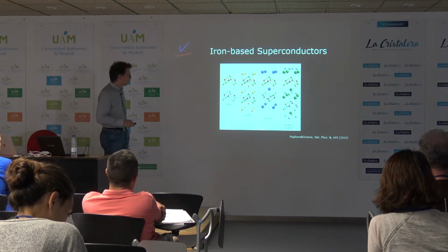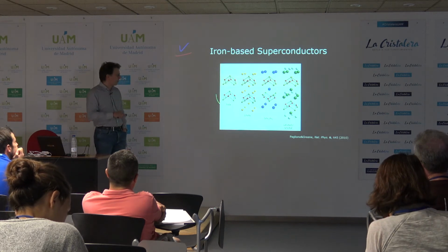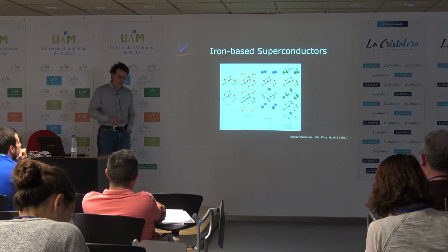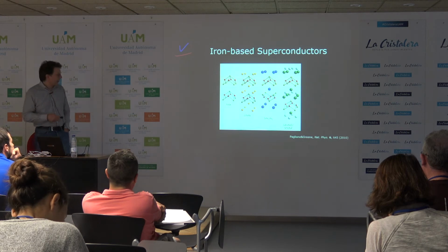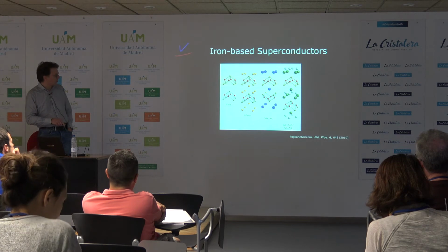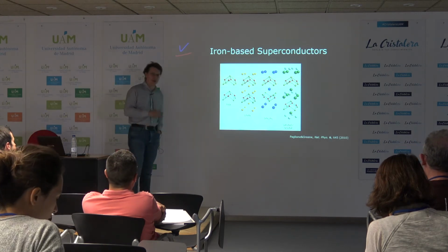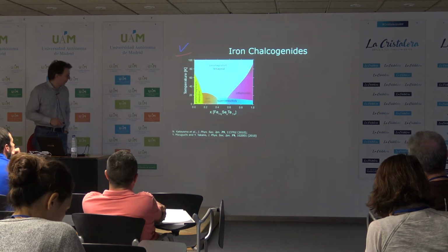the iron chalcogenide superconductors. And one of the reasons why we chose to study iron tellurium is because if you cleave the material, it's a non-polar surface, and you don't cleave into any of the dopant layers as you would do in the 1,2,2 compounds or the 1,1,1,1 compounds. So you can assume that your surface is reasonably representative of the bulk material.